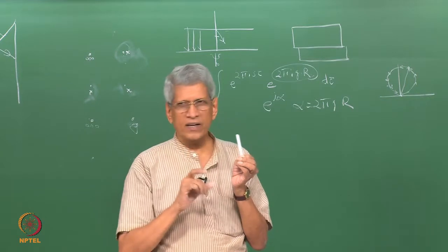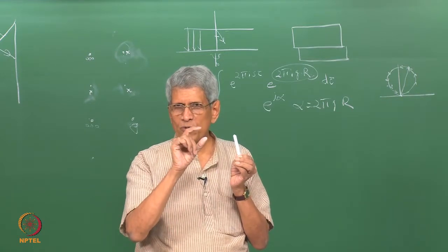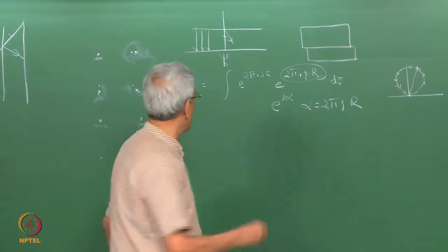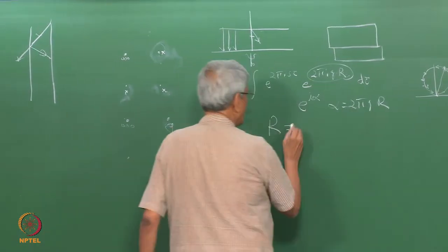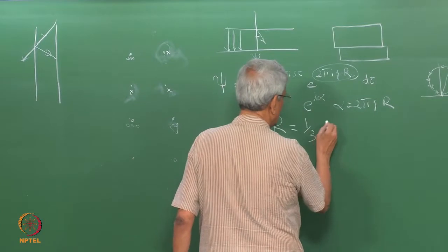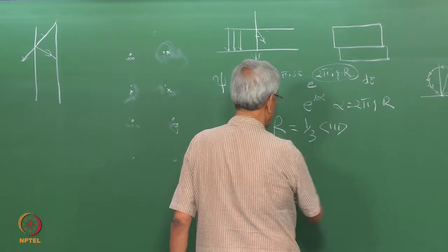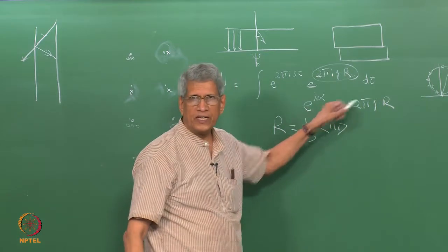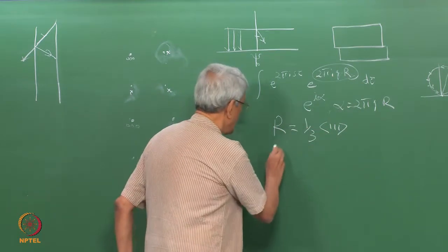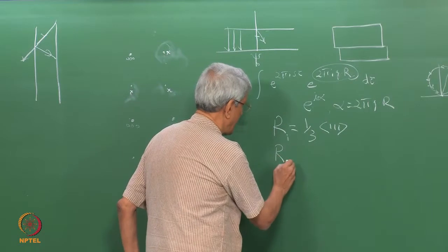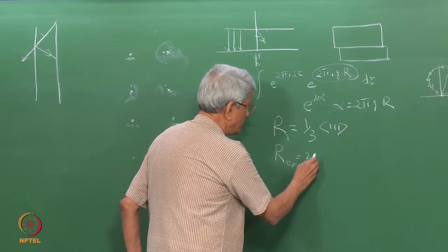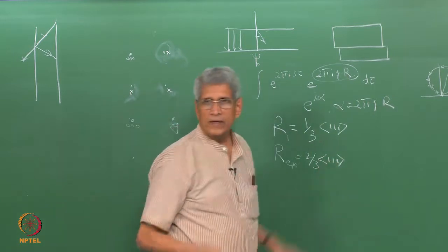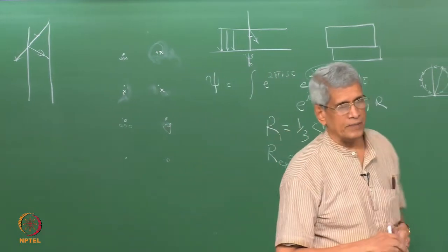In an extrinsic fault, what do we do? We modify 2 layers. So for an intrinsic stacking fault, R will be 1/3 <111>, and we have to choose the appropriate one depending upon which plane and which direction this will change. This is for intrinsic. For extrinsic it will be 2/3 <111>. Okay, this is going to be the fault vector.